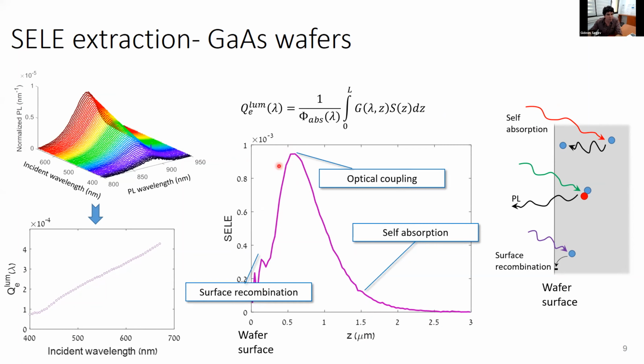We can test that this profile actually is physical. One way to do this is to throw it back into the equation here and see that we can reproduce the incident wavelength dependent quantum yield, and as you can see, it works pretty well. So this was all pretty reassuring, and we are very happy with these results, but we're still missing some stuff. For example, how do we connect surface recombination velocity or bulk lifetime to terms that we have here? A good way to do this would be through simulation.